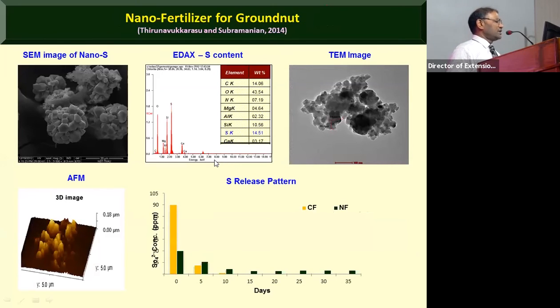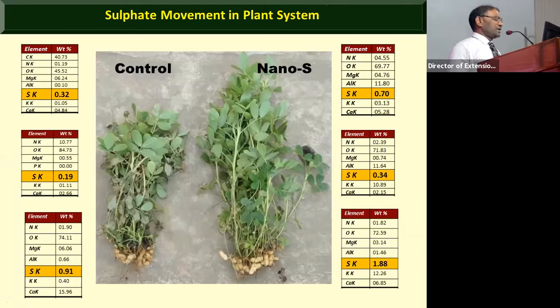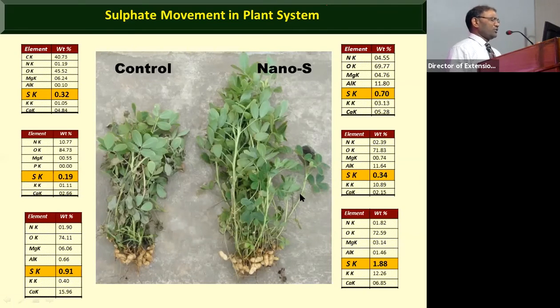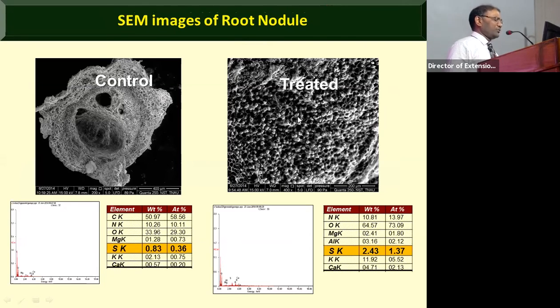I also developed a nano-fertilizer for groundnut made from zeolite. Zeolite is a clay-like mineral that is converted to nano size and loaded with sulfate, becoming a nano-fertilizer. With conventional fertilizers, plants use only 18–20 percent of sulfur, 20 percent of phosphorus, and up to 30 percent of nitrogen — the rest is wasted. With this nano-technology we are able to achieve 90 percent use efficiency. Plants treated with this nano-fertilizer are visibly healthier, with higher sulfur content and much denser nodules in legumes.